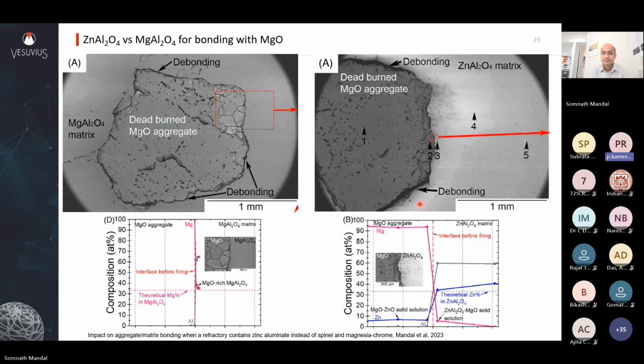Dr. Mandal, in terms of corrosion resistance, which one is more beneficial as compared to chrome, magnesium aluminate or zinc aluminate? In terms of corrosion resistance for copper slag, they are both very similar. You will probably have to use both of them and work on the ratio. Maybe 1:1 is a good starting point in the matrix. In terms of hot strength, if you compare a pure magnesium aluminate matrix versus a magnesium aluminate and zinc aluminate matrix, 1:1, you will have better hot strength in the combined matrix, because there is very high diffusion and solid solution between zinc aluminate and magnesium aluminate.